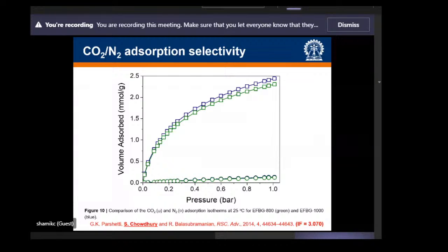So then what we did is, since this nitrogen is usually present at 0.75 bar, we took the nitrogen adsorption value from the 0.75 bar corresponding from the isotherm, and for the CO2 we took it from the 0.15 bar. From that we calculated, and we saw that the adsorption selectivity is significantly high. In fact, it was about 60 in one case, and in the other case it was around 67.